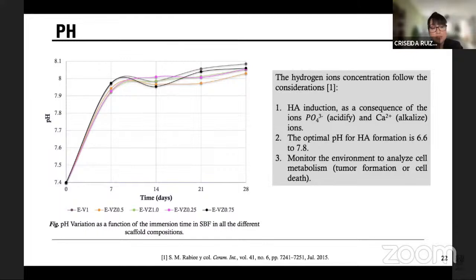The higher the saturation, the higher the apatite formation will be, and the lower the saturation, the more hydroxyapatite formation will be inhibited. This analysis of the pH variations as a function of the immersion time in the SBF, or simulated body fluid, allows us to know the behavior of the medium and the scaffold dissolution due to the hydrogen ions release. It permits us to know the acidity effect, and the alkalinity that occurs in the medium due to the amount of calcium ions released. It's important to comment that the hydroxyapatite formation occurs in pH values between 6.6 and 7.8.